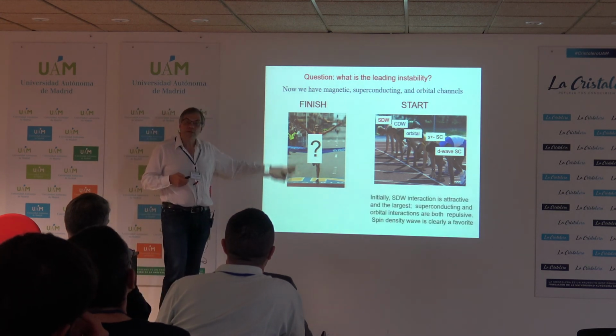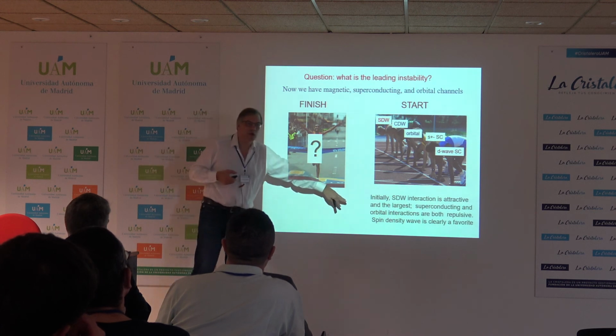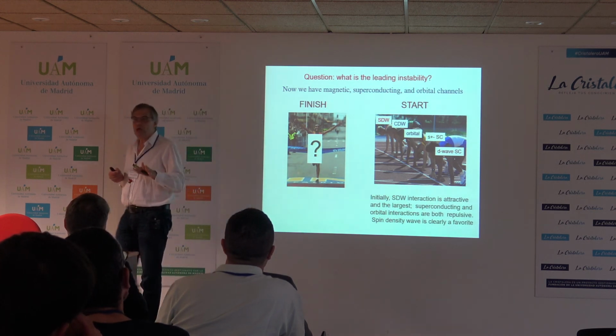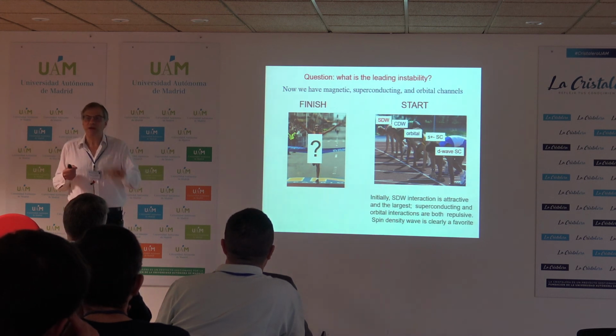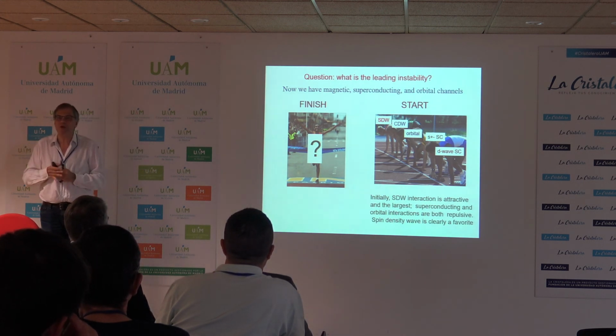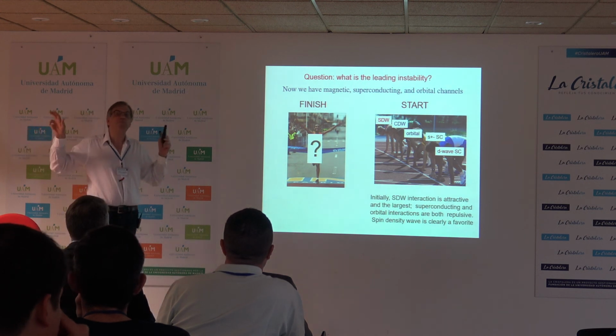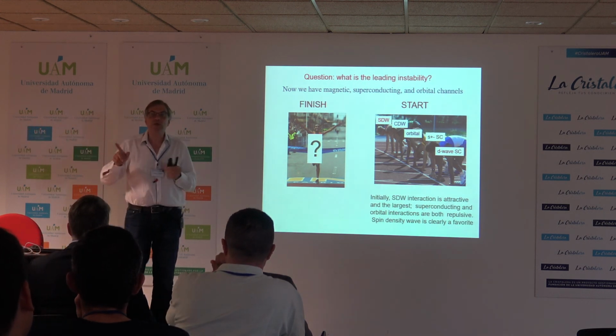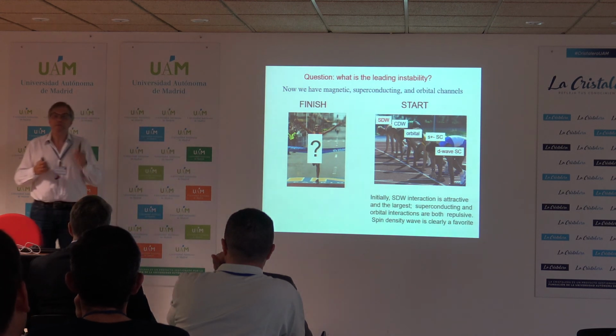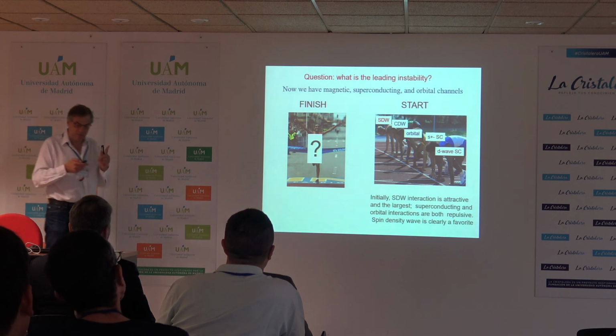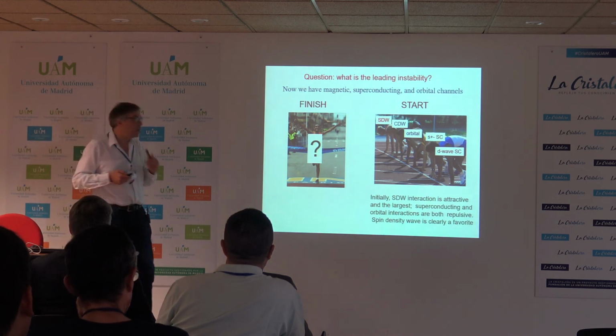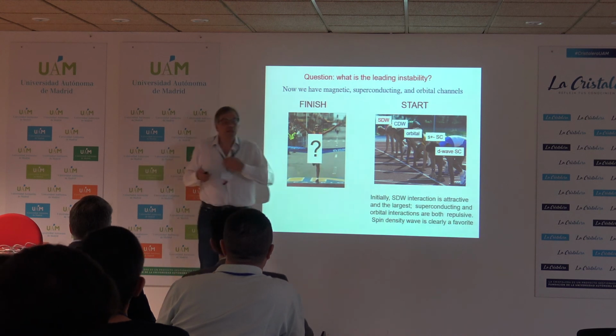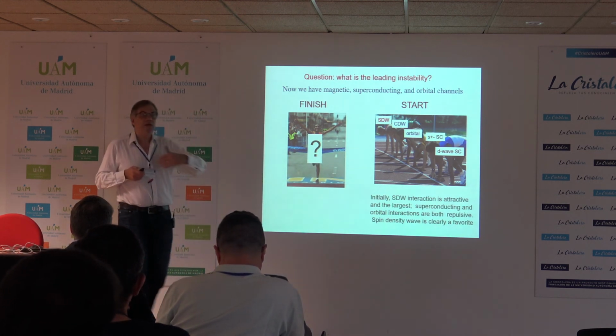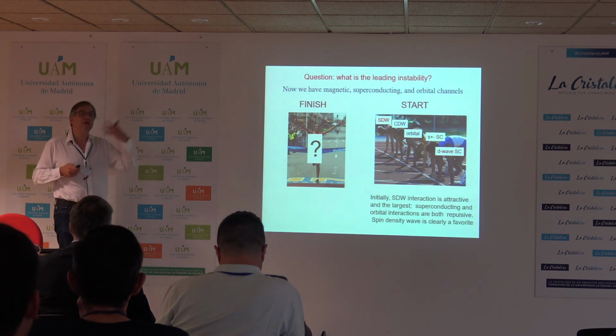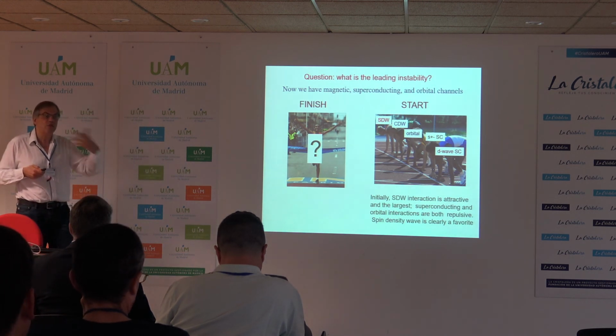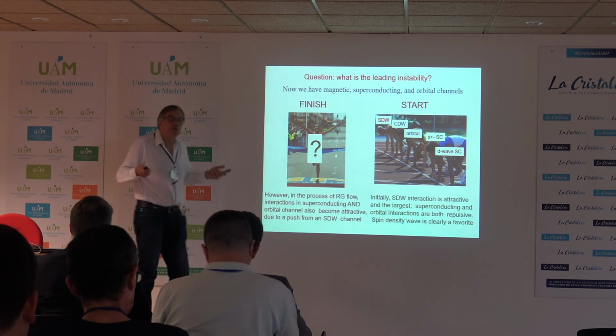And this is a nice analogy, but the real story is that you start with a situation when you have only spin density wave interaction effectively attractive. Remember, in order to get Stoner instability, you need repulsive interaction between particles. Stoner magnetism comes from repulsion. So repulsive interaction is good for magnetism, but bad for superconductivity, bad for orbital order. So you start with a situation where originally the system tries to develop spin density wave. But as I said, in the process, due to feedback effect, it also changes the sign of interaction in the 2 other channels. So the question is, what happens?